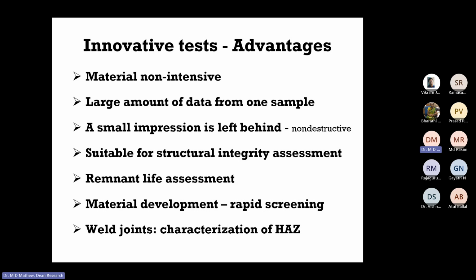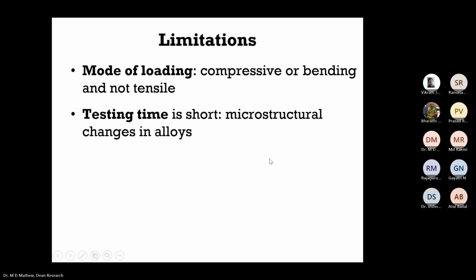So if you want to characterize the properties of the heat affected zone, there is no other method, whereas this method comes, it will allow you to do that. But it is not all rosy there. There are many limitations. The first and foremost is about the mode of loading. Most of the mechanical tests that we do are tensile tests. Loading is tensile. But in these innovative tests, the loading turns out to be either compressive or bending mode.